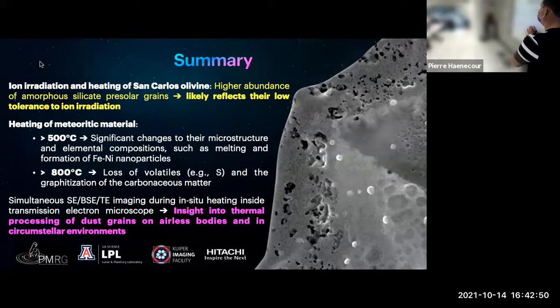Just to summarize some of the information I showed you today: ion irradiation of San Carlos olivine is consistent with what we expect in circumstellar environments, with a higher abundance of amorphous silicates. For the heating of meteoritic material, above 500 degrees, you will see significant change to both the microstructure and elemental composition, such as melting or sintering and formation of iron-nickel particles. You get larger and larger iron-nickel particles the longer and the higher the temperature that you keep the sample at. And at temperatures above 800 degrees, you lose all the volatiles. Sulfur is completely lost into the vacuum, and the iron is contributing to those iron-nickel particles, and then graphitization of the amorphous carbon.